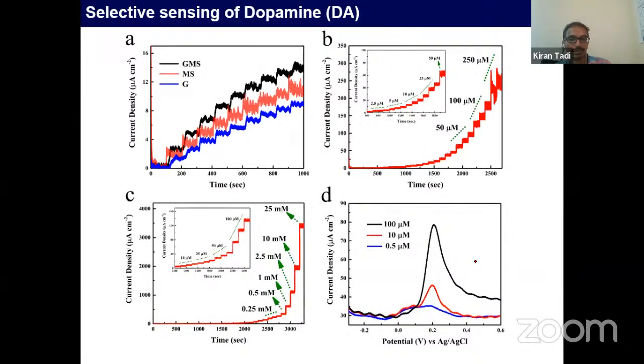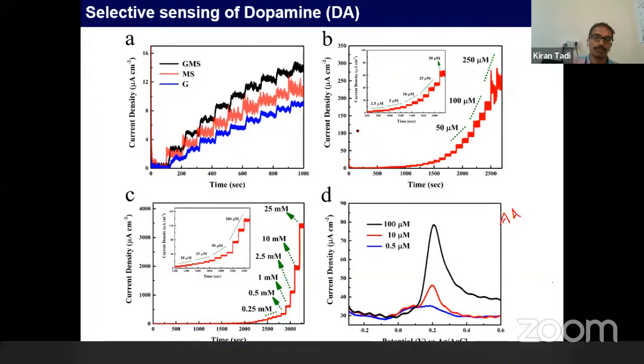Using differential pulse voltammetry (DPV), we detected dopamine in the presence of ascorbic acid. We took ascorbic acid even at 10 times higher concentration, but we didn't find any signals corresponding to it, we didn't find ascorbic acid signals here. So in this way, we prepared the graphene-protected MoS2 sensor, which is highly stable, sensitive and selective, made using the van der Waals heterostructure method.